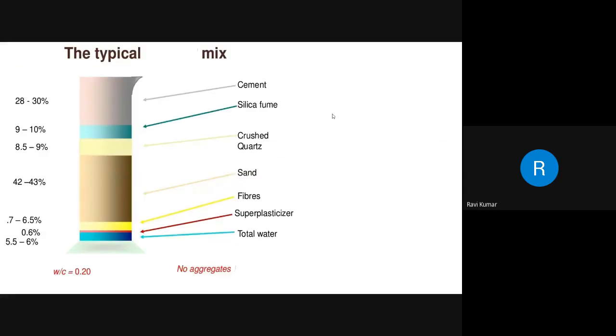Now the typical mix, with a water cement ratio of 0.2 for the RPC, in terms of percentage: cement 28 to 30%, 9 to 10% silica fume, 8.5 to 9% crushed quartz, 42 to 43% sand, 6 to 7% fibers, 0.6% superplasticizer, and 5.5 to 6% total water. There is no aggregate in this mix.